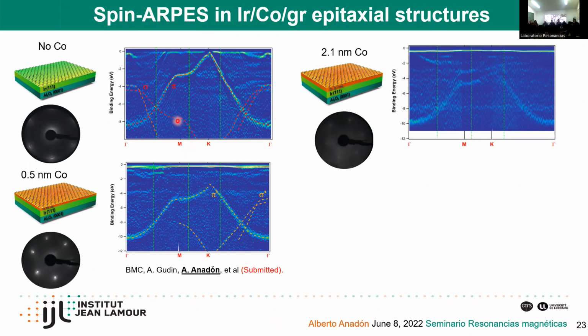This image shows the bands of an iridium graphene system. And you can see here the pi bands and the sigma bands of graphene. This is 62 electron volts of photon energy. And then when you grow the cobalt and you intercalate, you see this same shift in the bands that I showed just a few slides ago with XPS. And this is related to this electric field that I was just discussing.